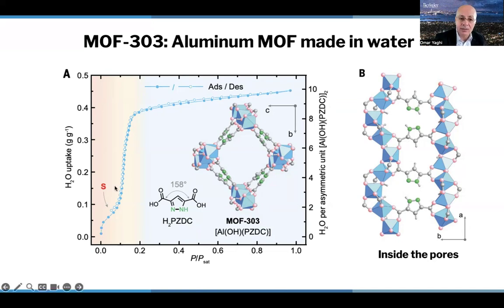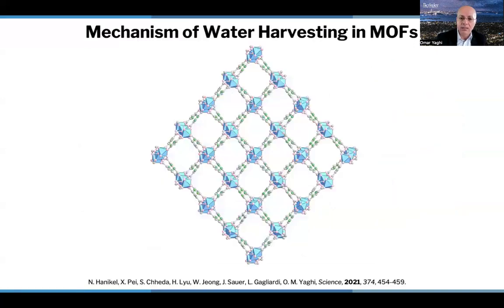But you see here in this isotherm that this material already could take up water from a relative humidity of 5%. Most water is taken up at a humidity of 10%. Now, if this material works at low humidity, as you see here, it certainly would work much better at higher humidity. So we don't need to necessarily make a new MOF for each humidity level. The minimum humidity level is 5% here, so anything higher than 5%, this MOF would work for that.